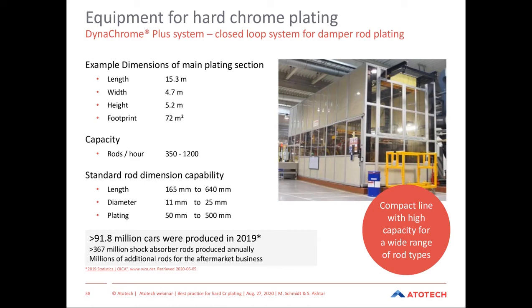And then as an example, there's high-speed plating equipment, in this case for automotive shock absorbers. It's our Dynachrome system. With a footprint, you see on the picture, it's a completely housed system. So all the chrome and all the emissions are staying inside the enclosure. So workers don't get in contact with the chemistry anymore. And with a footprint of only 72 square meters, these kind of lines are able to produce 350 to 1,200 rods per hour. So plating of 5 to 6 million shock absorber pieces per year is possible, with the plating length of about 500 millimeters and diameters from 11 to 25 millimeters. We're plating here really to the required thickness without any overplate.